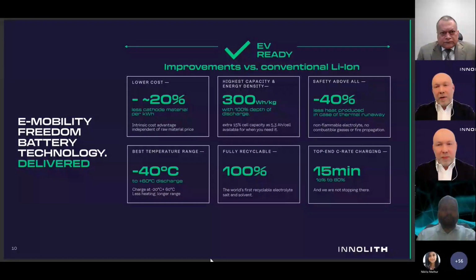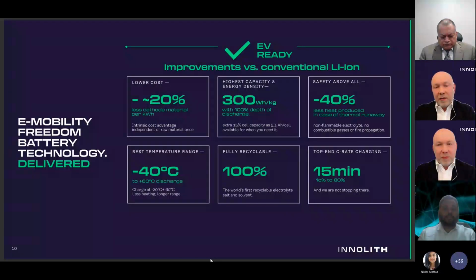Yes. Our current battery cell is made in 21700 format. We have high utilization of cathode, and that's why we need 20% less metal inside of the cell, which brings its cost down roughly by 10%, because cathode is approximately 50% of the cost of a battery cell. Energy density is 15 to 20% higher than that of the conventional cells in the market, 300 watt-hours per kilogram, and that is with 100% charge and discharge, full capacity available.